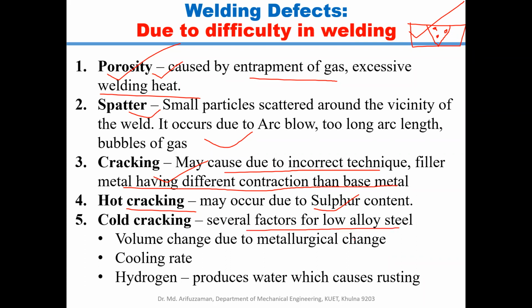And the cold cracking, several factors for low alloy steels, like volume change due to metallurgical change. When the volume change occurs, the heat affected zone has a different volume change than the welding zone. Because of that, cracks might occur in these regions. And the cooling rate, if the cooling rate is very high, then there will be very high contraction, and because of that contraction, the stress mismatch will occur between the base metal and the workpiece on the welded zone. Then there will be cracks. And also hydrogen embrittlement. When the hydrogen reacts with environmental oxygen and produces water, which causes rusting on the edges or surfaces of the material, you cannot avoid these defects.